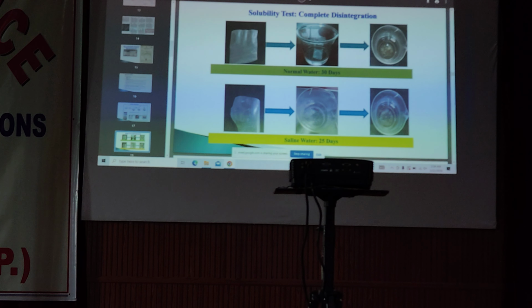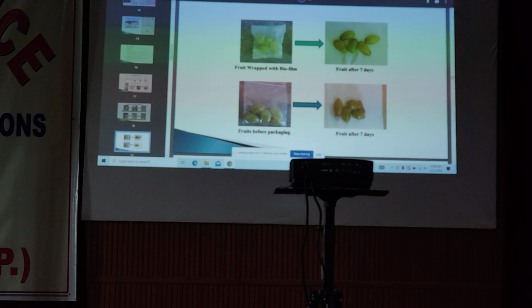And these are images showing that when we put it in water, we observe that in 30 days it is completely disintegrated, completely solubilized. In 30 days in normal water, in lab testing 25 days in saline water and in sea water as well.